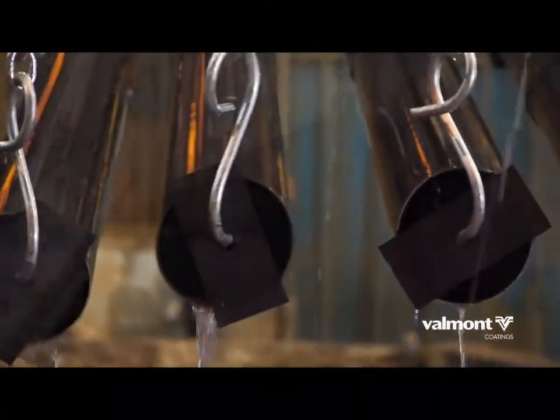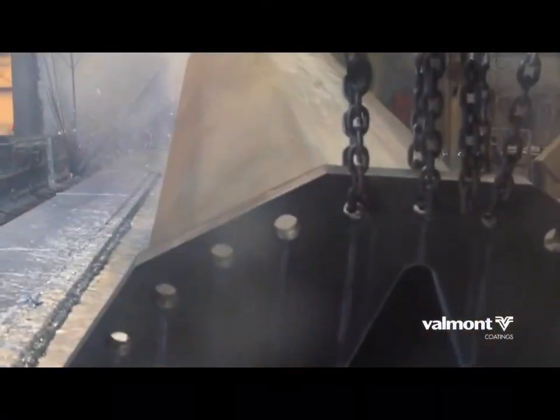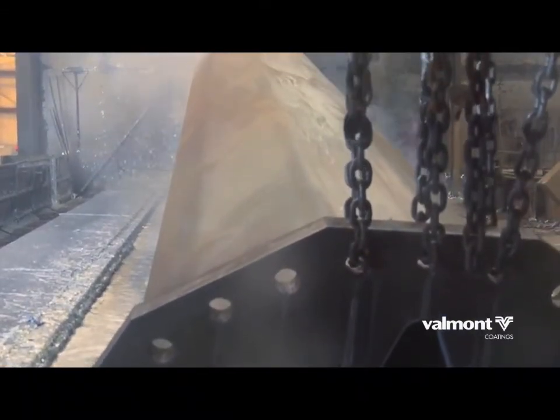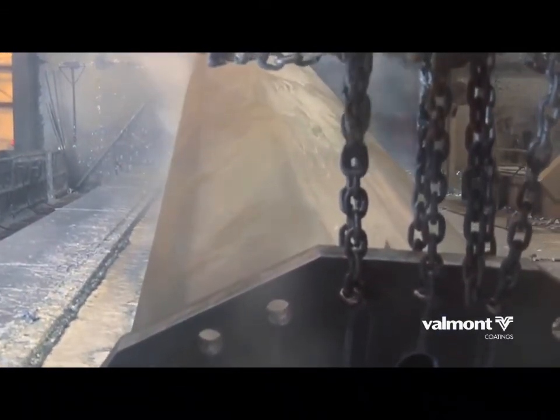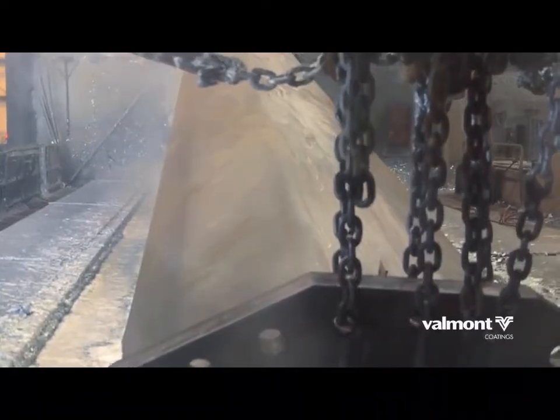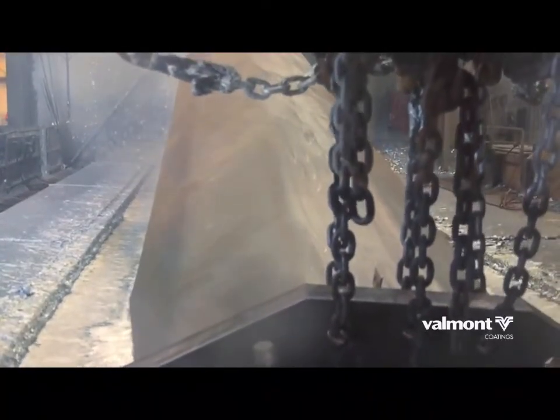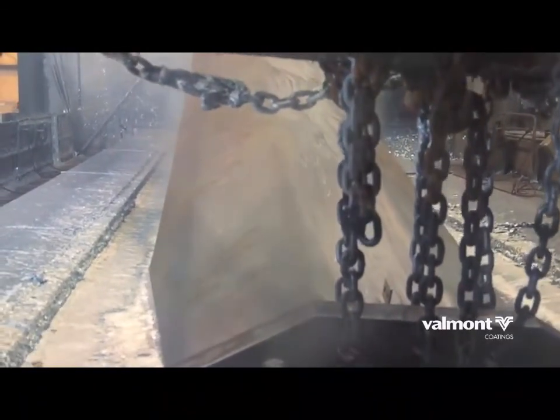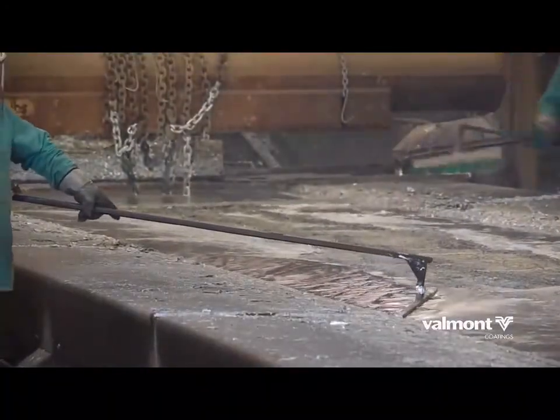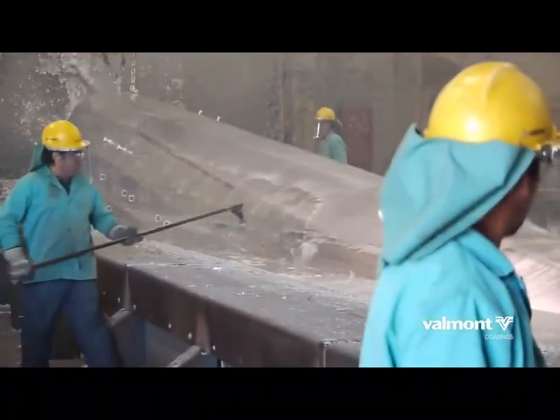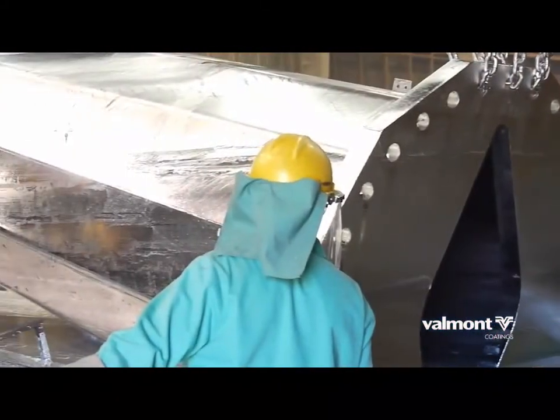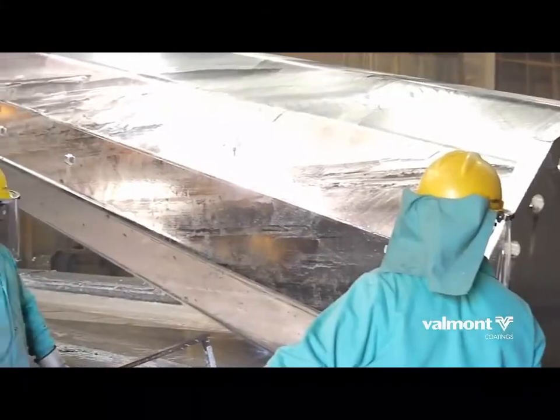Once the structure is clean and dry, it is dipped into a bath of molten zinc. As the material is immersed, the zinc will flow in and around the entire structure, protecting all surfaces. While in the bath, chemical reactions take place between the zinc and the iron in the steel to form a series of zinc-iron intermetallic layers and an outer layer of pure zinc.